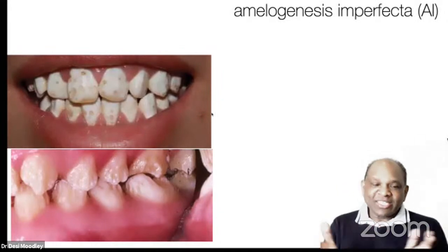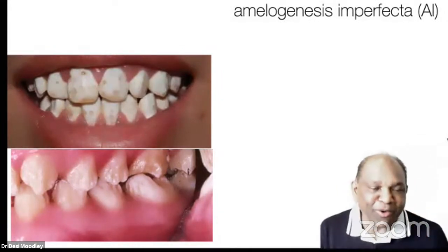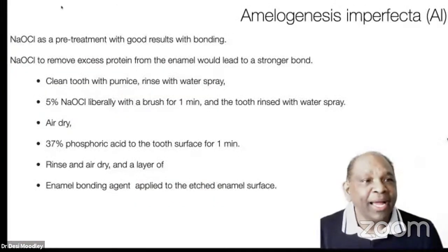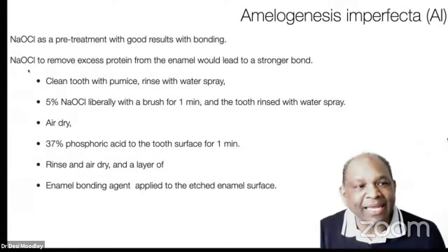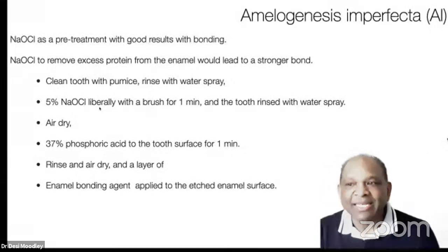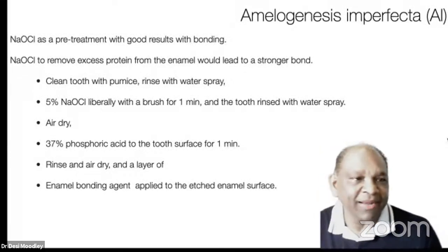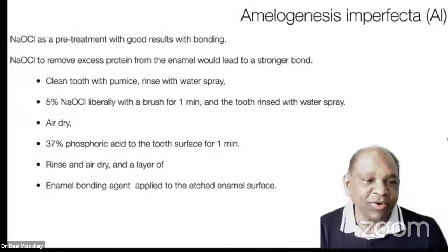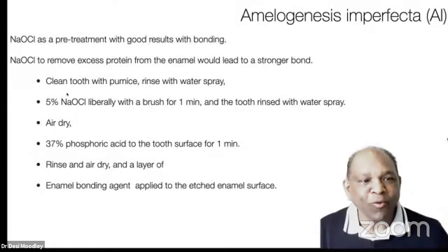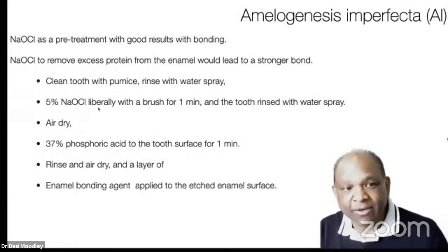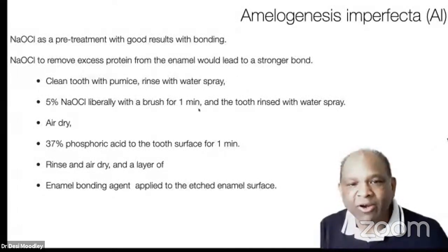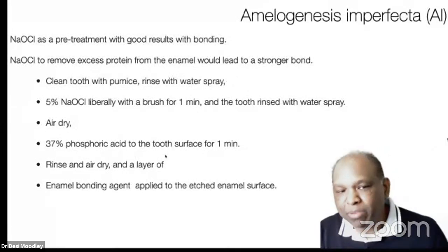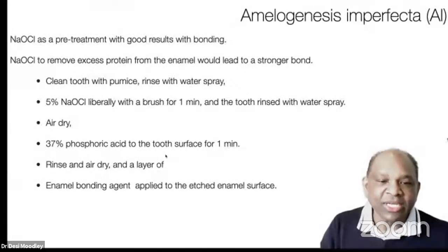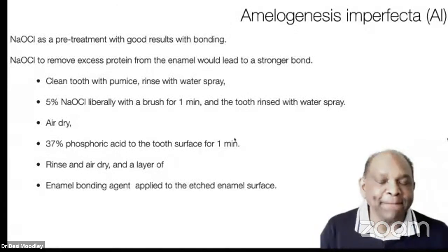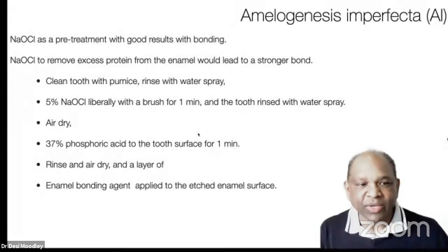With regards to amelogenesis imperfecta, it is always a problem, especially with bonding. I found that some articles state that sodium hypochlorite 5% tends to improve retention or the bond strength. You vigorously use 5%, liberally, sodium hypochlorite for 1 minute, rinse off, and then etch, and then bond. So it seems to be working well, getting better results using sodium hypochlorite rather than just going straight for etching and